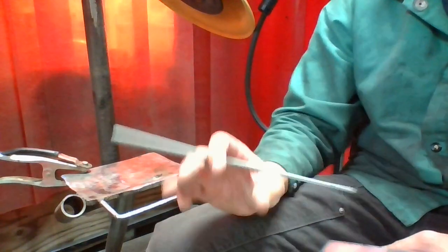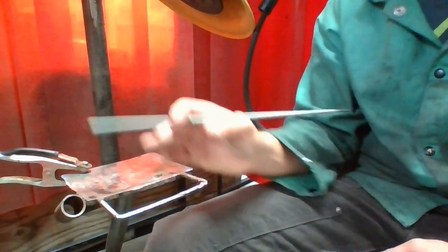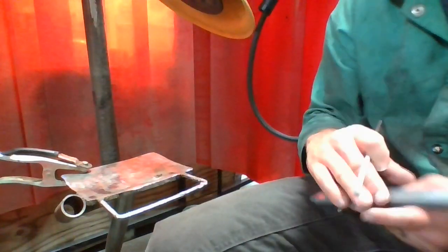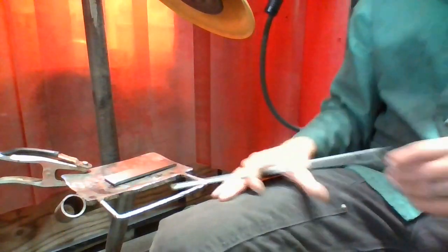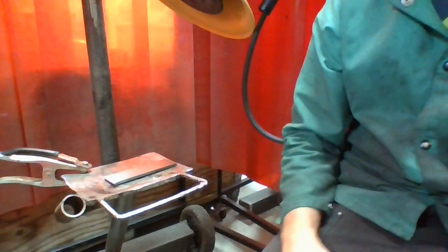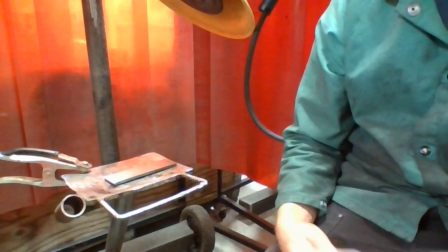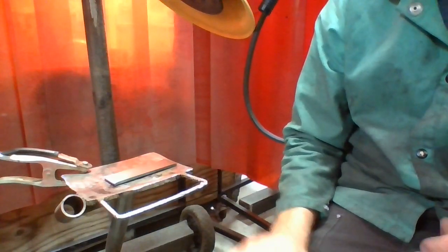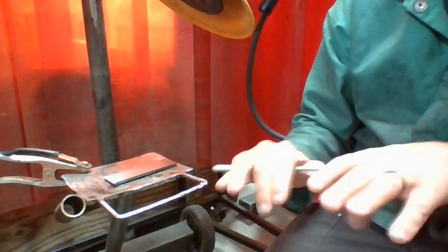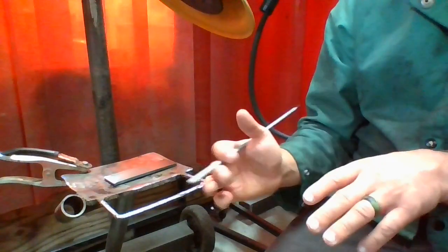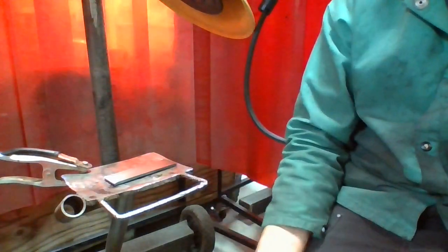And the reason you whip out of the puddle is to let the puddle cool down, and then you come back to add some more material. You whip out, let the puddle cool down, come back. And that technique is used on open root butt welds, like for pipe, where you have an open root. You have to let that puddle cool down, or you're just going to blow through it.